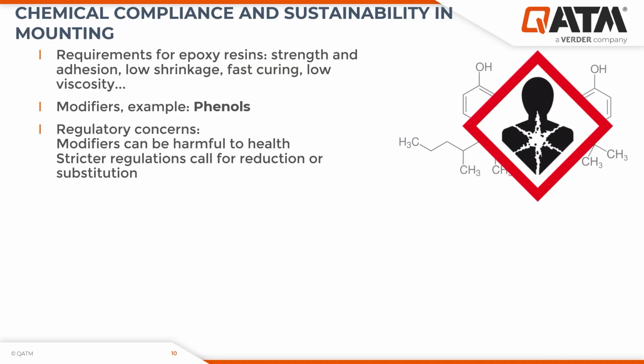Stricter regulations are now pushing for a reduction or substitution of these potentially hazardous components, especially considering that these phenols may be used in classic epoxy resin formulations by up to 30 to 60 weight percentage and are not incorporated into the epoxy resin itself and can be released during grinding and polishing processes. As a result, there's a clear trend towards safer and more sustainable epoxy system solutions, and modern developments focus on formulations with fewer harmful modifiers without compromising the performance. So basically keeping the low viscosity, good adhesion, and the fast curing, all without compromising the performance.